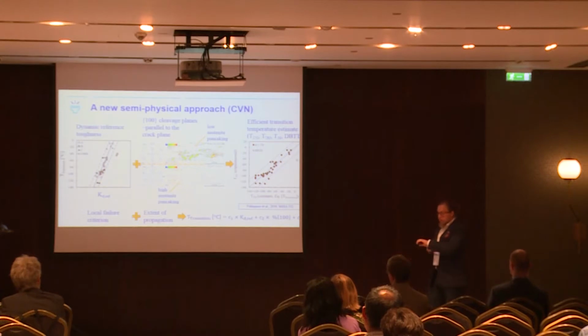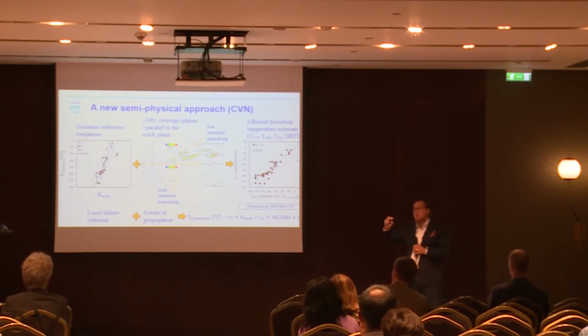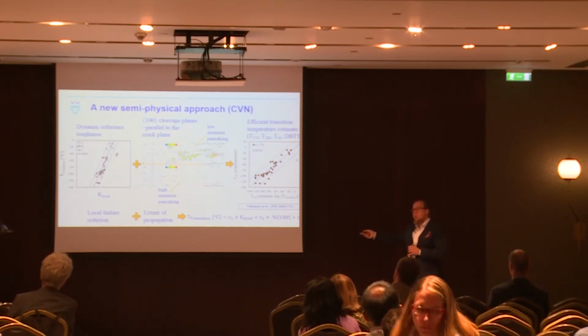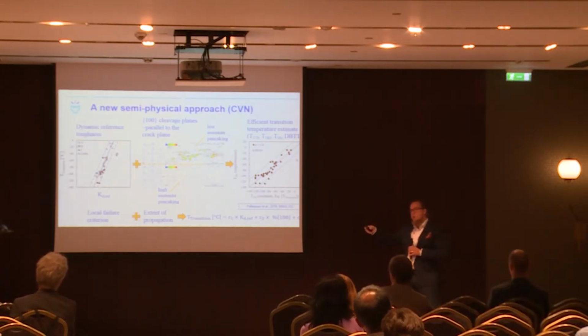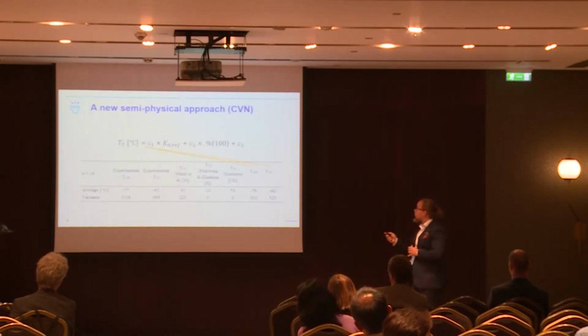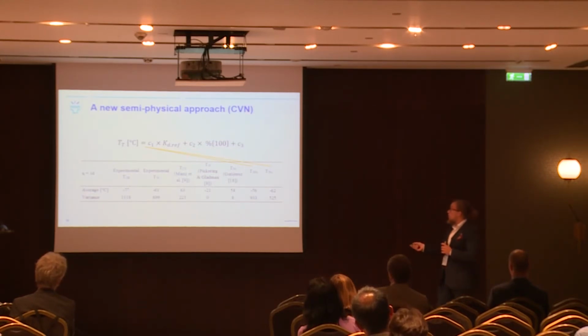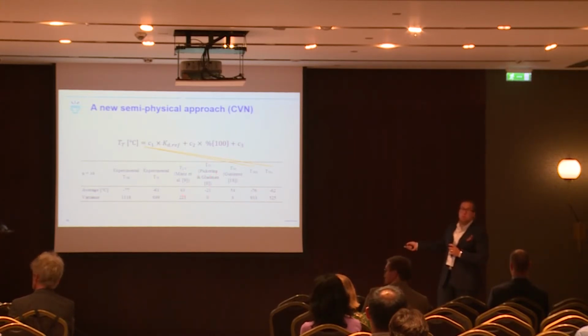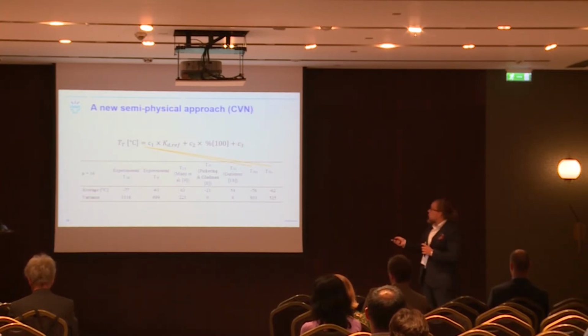And also, the fractographic evidence shows that the grain size around these inclusions that nucleated the failure corresponds to that level of 80 to 90% cumulative distribution. So just a quick comparison of this estimate to the literature. Well, the level is okay, of course, due to fitting with the data, but more importantly, with these two parameters, we are able to capture almost all of the variance in these experimental results.